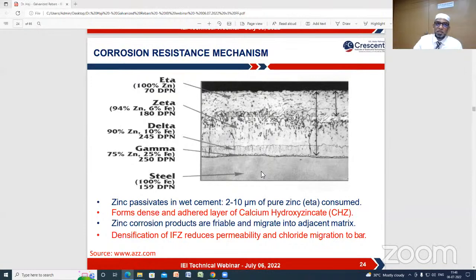By simple dipping in the galvanization process, depending upon the curing conditions, the surface immediately, where the zinc touches the steel rebar, you will have an alloy of 75% zinc and 25% Fe. If you go up, the zinc content is more, and the topmost layer is pure zinc.